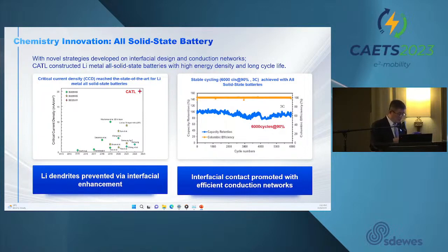The challenge is because of the lithium dendrite. This is a big challenge, which can lead to battery failure and safety issues. CATL has engineered an advanced electrolyte interface. By implementing our mechanical enhancement technology, we achieved a critical current density of 20 milliamp per square centimeter without observing any dendrite growth.